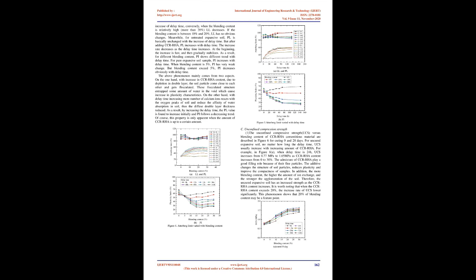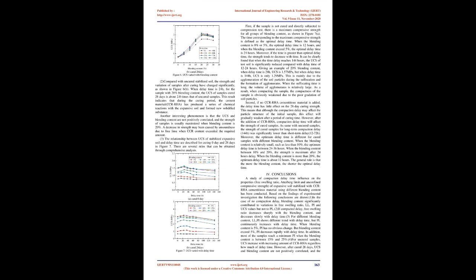2. Figure 5 shows the influence of delay time on LL, PL, and PI with different CCR-RHA content. When the blending content is relatively low, less than 10%, LL increases with the increase of delay time. Conversely, when the blending content is relatively high, more than 20%, LL decreases. If the blending content is between 10% and 20%, LL has no obvious changes. Meanwhile, for untreated expansive soil, PL is basically unchanged with the increase of delay time. But after adding CCR-RHA, PL increases with delay time. The increase rate decreases as the delay time increases. At the beginning, the increase is fast, and then gradually stabilizes.